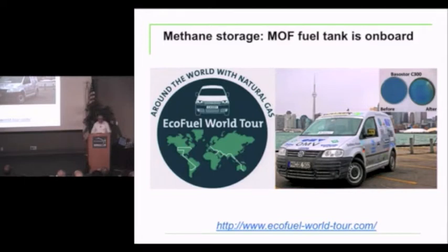And so really this is very exciting because as of today, the MOFs have been tested by BASF for over 100,000 cycles and for the lifetime of an automobile. And the MOF material never has to be changed, never has to be regenerated as you fuel and defuel, but it can sit in the car for the lifetime of the car.